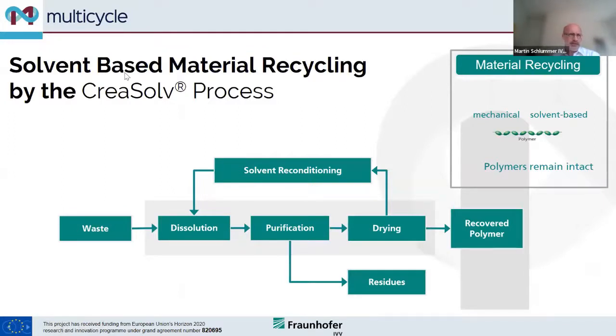It is a solvent-based process, but it is not a chemical recycling. It is a material recycling. This is very important. It is like mechanical recycling in that we always keep the polymer intact, so we don't hamper the polymer. We only dissolve it and keep the polymer all the time during the process. After dissolution, we have the chance to purify better than in a melt state of a polymer. Of course, in the end, we have to recover the solvent by drying processes and get the recovered polymer.